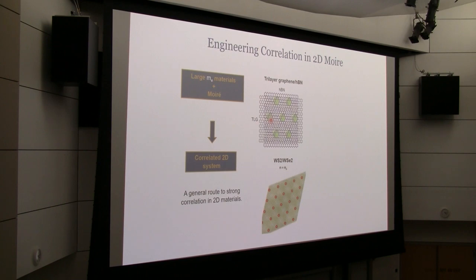Okay, with that, I would like to just conclude. I hope I have shown you that by borrowing Mott's idea, there is a very general way to engineer strong correlation in Van der Waals heterostructures. Just by making Moire superlattices, you can have larger period. Naturally, that tends to give you stronger correlation. Although I talked about 2 systems, transition metal dichalcogenide and trilayer graphene, this should be applicable to almost any 2D semiconductors. So there are many different systems one can play with.